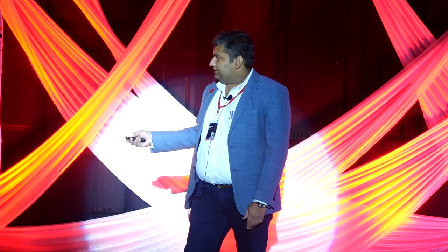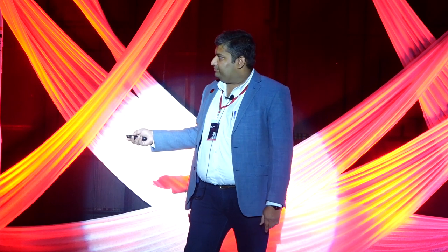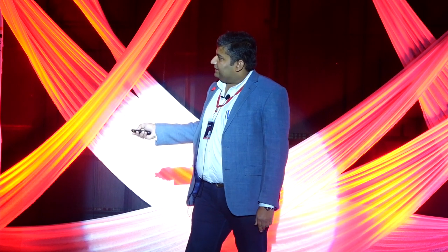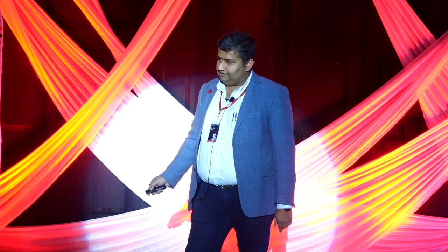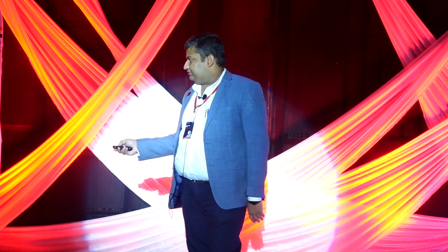And then we tried to lift out a lamella from this pellet, what you see, typically a button cell, compressed at different pressures, where we can remove a lamella by using a focused ion beam system, and then thin the interfaces, which are very critical to understand what happens across. And then you see here, typically of the order of around 100 nanometers, we were able to thin them. And the whole lamella, which is unusually large, provides the mechanical strength for that.